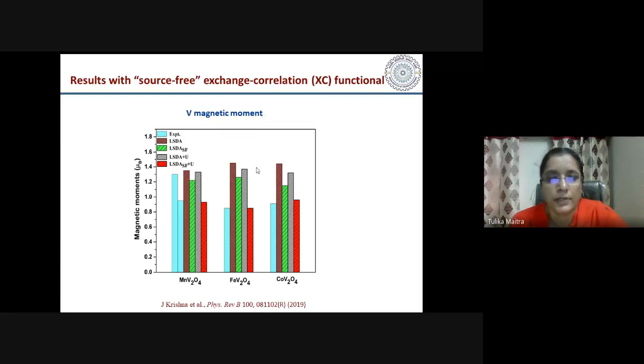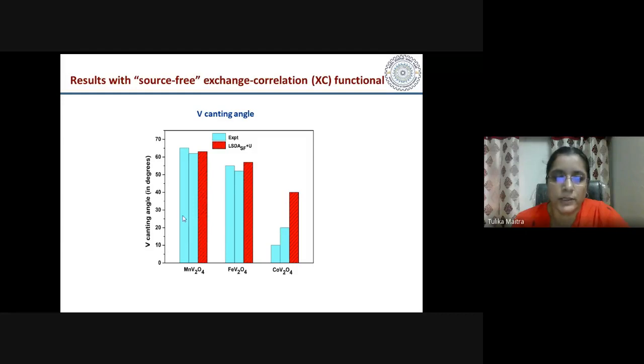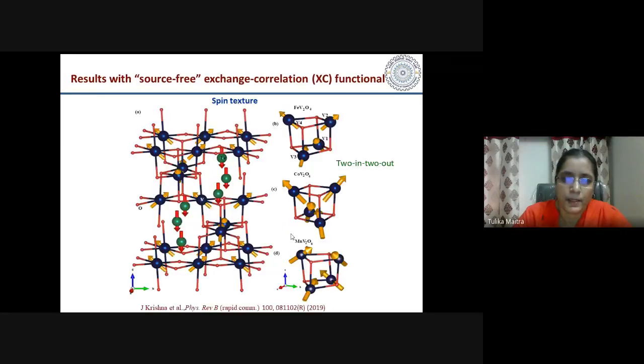And what we find is that by using the source-free exchange correlation functional, we found that the moment is really low and it matches with experiment for all three systems. Okay, so not only the low moment, we also find the vanadium canting angle in the non-collinear ground state. We find that the canting angle also matches the experimental values, and this is the complete non-collinear magnetic state that was calculated by our calculation. And we could derive this 2-in-2-out structure for FeV2O4 and CoV2O4, and the structure which was found for MnV2O4 also matches very well with the experimentally observed one.